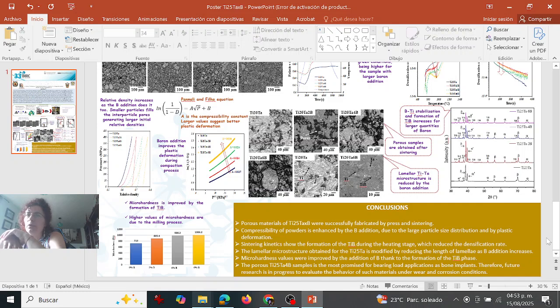The microhardness values were improved by the addition of boron thanks to the formation of the titanium boride phase. And the last conclusion was that the porous titanium 25 tantalum 4% boron sample was the most promising for load bearing applications, for example, for bone implants. And therefore, future research is in progress to evaluate the behavior of such materials under wear and corrosion conditions as we need for biomedical applications.